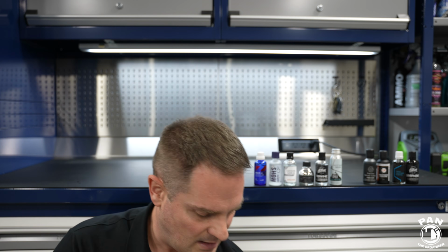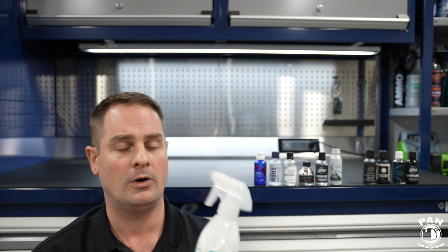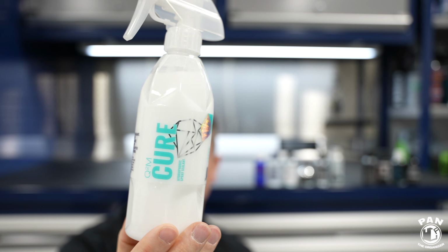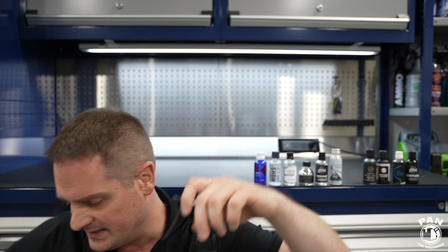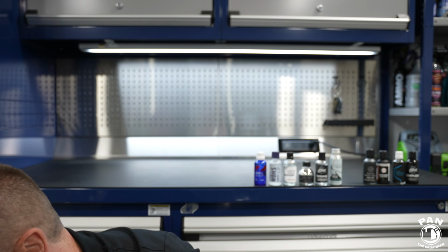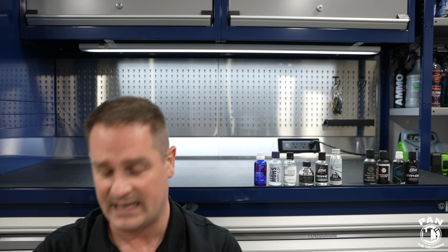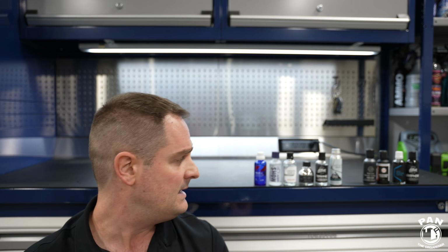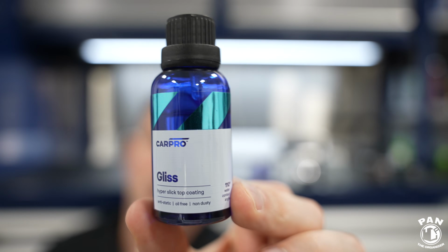So they continue to cure in the days and weeks following the application. So this helps. Pretty much all the companies, again, have a silica spray sealant. We have CarPro Reload for CarPro, Gyeon Cure for Gyeon coatings, and G-Technic has C2V3. Basically, for any ceramic coating that you apply, the company usually has some sort of silica spray sealant, or some companies also offer toppers that help prevent that, as we mentioned a bit before. Again, follow the instructions for the specific topper. But for example, for CarPro C-Quartz UK 3.0, 3 to 4 hours after you applied the coating, you have to apply CarPro Gliss.